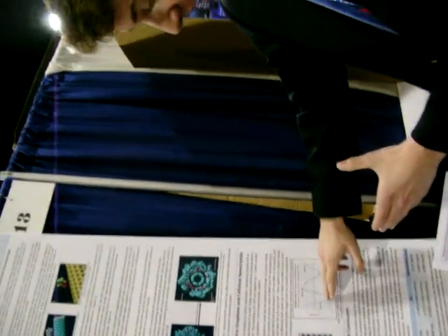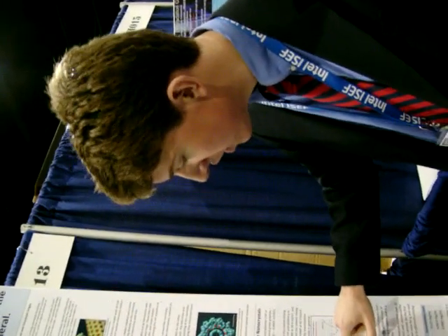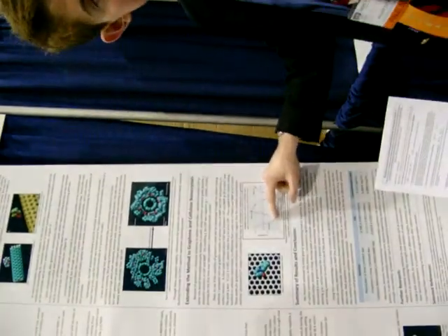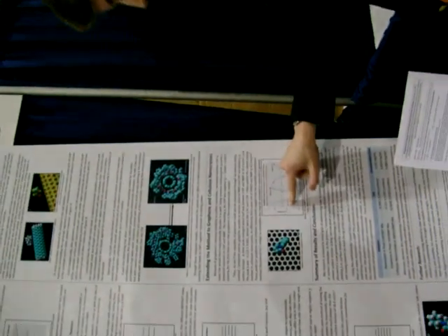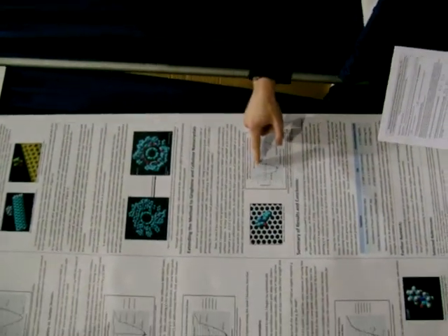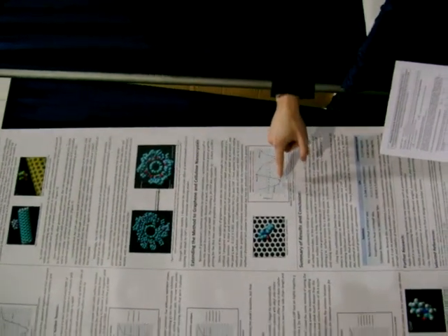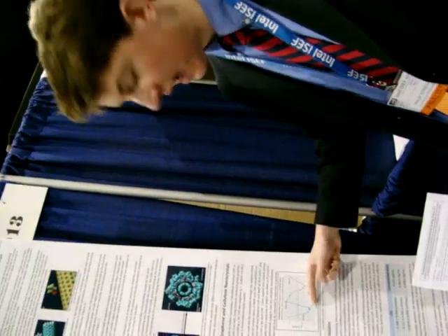And so I was thrilled to find that chi for graphene in CHP was actually negative, which proved for the first time that graphene is thermodynamically soluble. And I then constructed this peak for graphene, applying my method and mixing cyclohexylpyrrolidone, CHP, and NMP. And this peak had a chi that was twice as negative as the chi for just pure CHP alone.